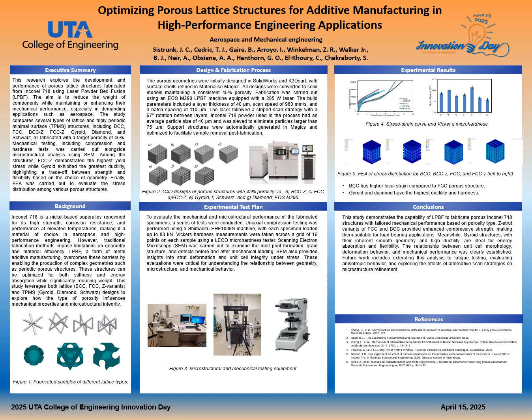On the other hand, the gyroid and diamond structures, which belong to the TPMS family, showed greater ductility and energy absorption. The gyroid, for instance, experienced the highest compressive displacement, around 4.8 millimeters, making it a great candidate for applications where flexibility and energy dissipation are more important than raw strain. In terms of hardness, the diamond structure exhibited the highest value, about 421 HV, while gyroid had the lowest at 337. These results highlight the trade-offs between hardness and deformability in different porous architectures.